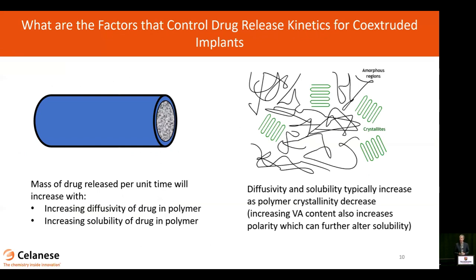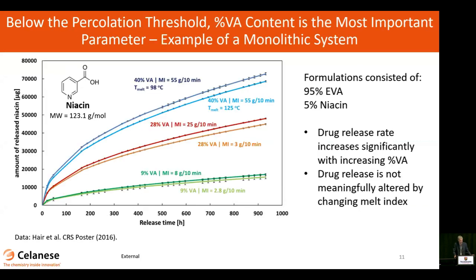That's because of the characteristics that matter for the drug to escape through this device. If it's going to escape radially from this multilayer implant through that outer membrane, it has to dissolve and diffuse through that membrane. So the solubility of the drug in the membrane and also the diffusivity of the drug through that membrane layer is going to be a function of how much amorphous content is in the material. Right? Because these molecules will not diffuse through the crystals. The kinetics are not sufficient for that to happen.